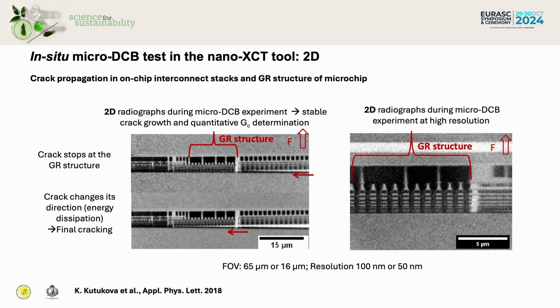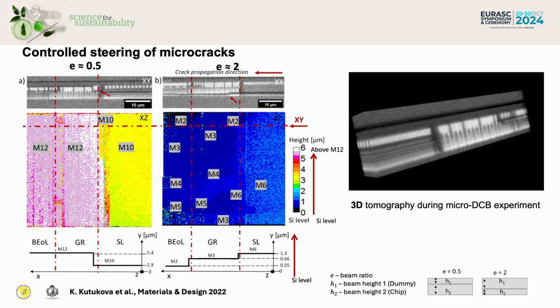On the right-hand side, you see how the crack is propagating, and the crack is propagating into the chip. And here you see 2 different things. Here the crack stops before the guarding structure, but if you increase the force, then the crack goes further. Okay, and now on the right-hand side again, now it's 3-dimensional in tomography. You see again the crack, how it is propagating, okay?